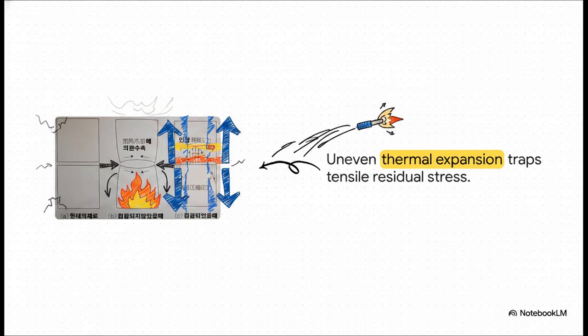So you end up with this massive, vicious tug-of-war. The outer edges are being pushed out, experiencing what we call compressive stress, while the center weld is stretched unbelievably tight. It literally traps tensile residual stress right there in the middle of the joint.